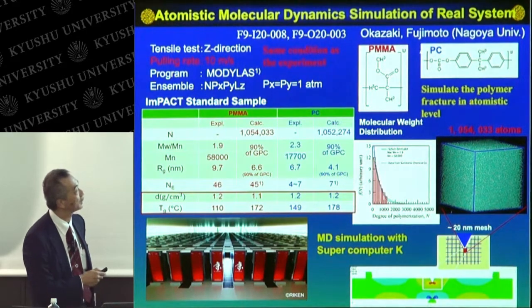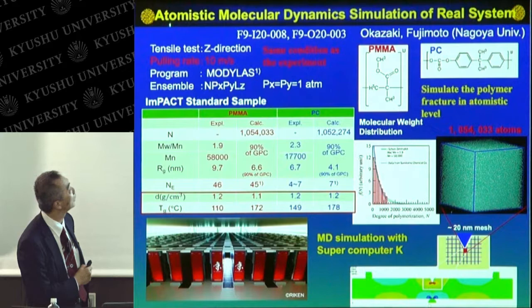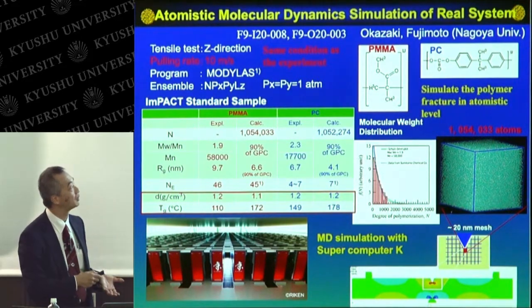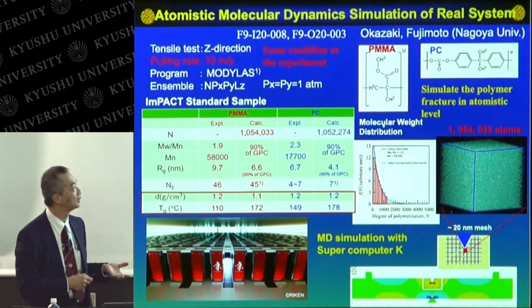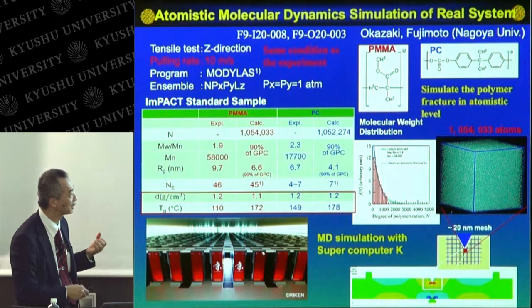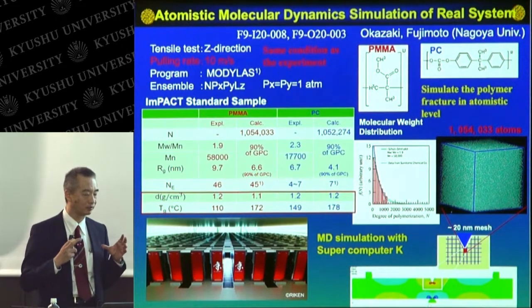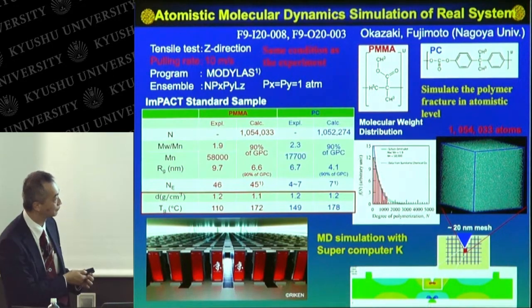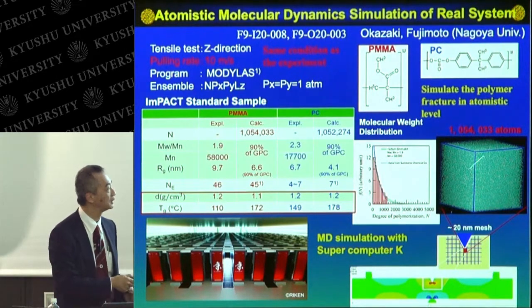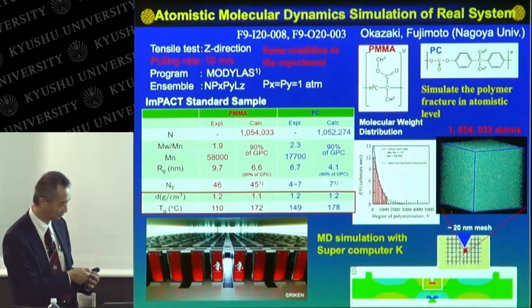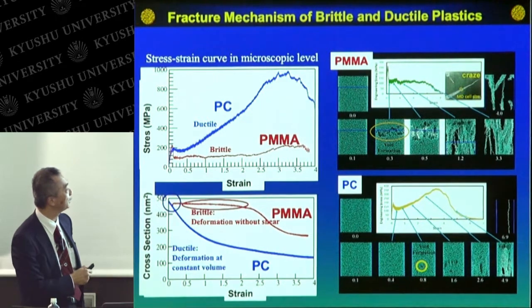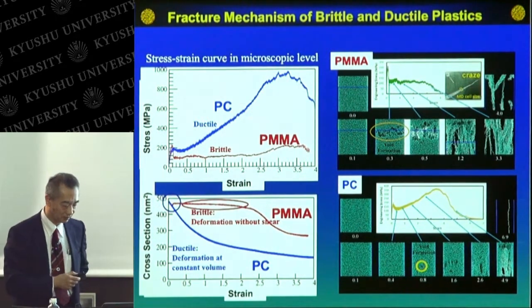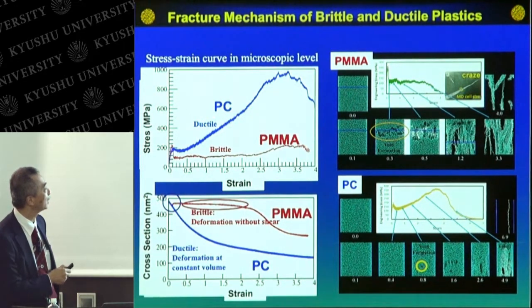And also Professor Okazaki at Nagoya University performed atomistic molecular dynamics simulation of the real system. They consider real polycarbonate and PMMA or polystyrene, which includes the real molecular weight distribution like this. And they used the supercomputer K to realize polymer fracture at the molecular or atomistic level. They used about a million atoms in these cells. And in this simulation, they realize the difference of the fracture behavior between polycarbonate and PMMA.